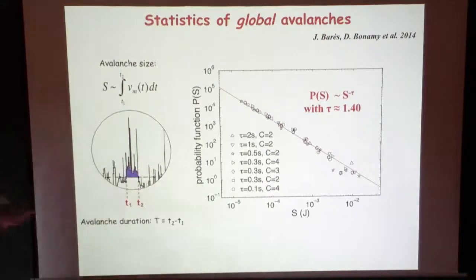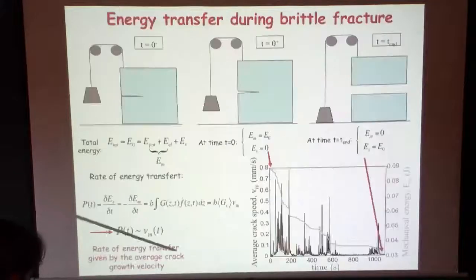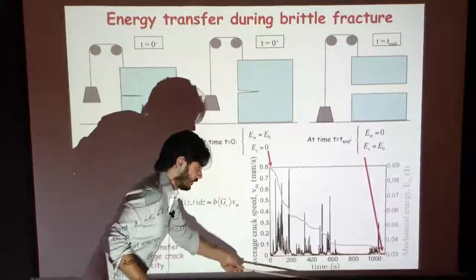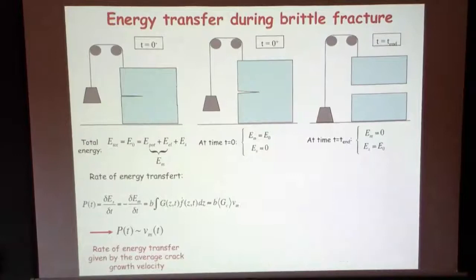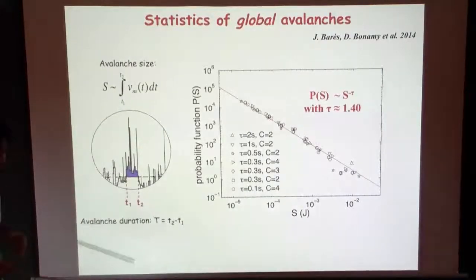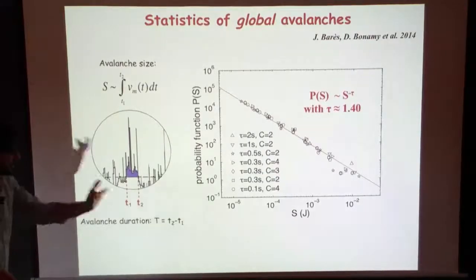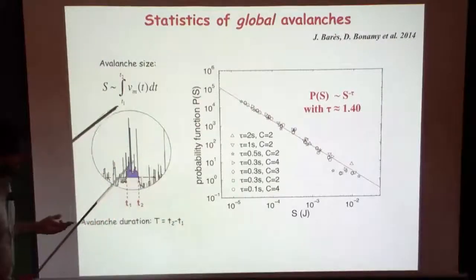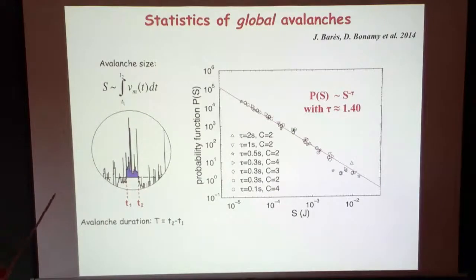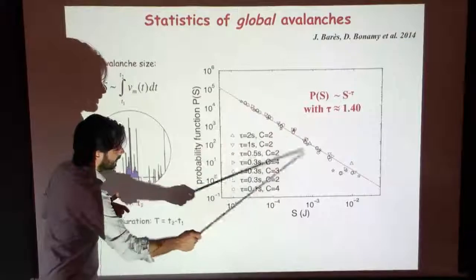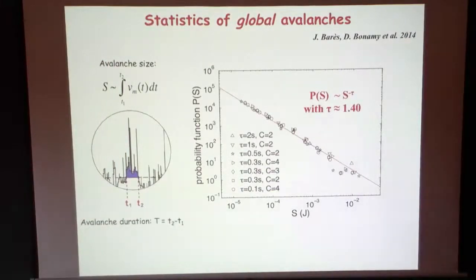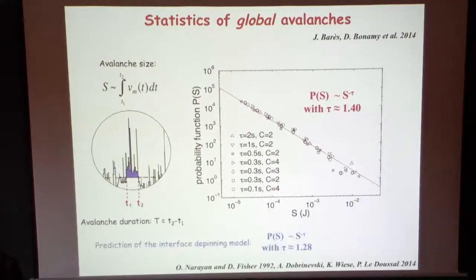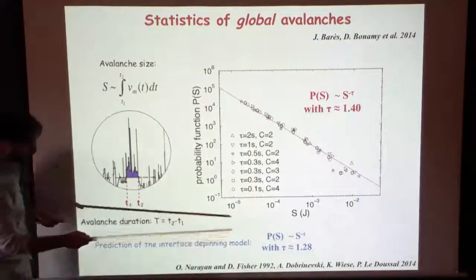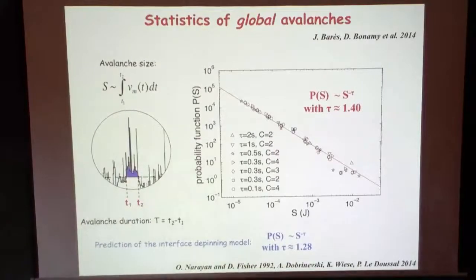Okay, as usual, you never really go to exact zero velocity, so you need to define a threshold, and you define avalanches as bursts of transfer of energy, and you get the amount of energy transferred by just integrating this curve. Remember, V is the power of energy dissipated, so you integrate it over time, and you can look at the statistics then, statistics of size of avalanches defined in energy. From an energy point of view, they observe power law statistics, an exponent close to 1.4. That you can compare with the prediction of the depinning model, that is slightly bigger. Okay, this also we can discuss. Different scenarios why it's slightly bigger, but the comparison is not completely stupid.